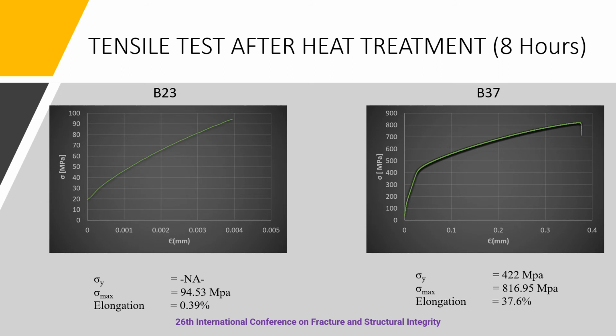When we carried out the tensile test on both the alloys after 8 hours of heat treatment, the nature of B37 did not change, while the nature of B23 changed completely. After the heat treatment, the yield strength of B37 was 422 megapascal, while the ultimate strength and elongation were 817 megapascal and 38% respectively. But when B23 was subjected to heat treatment, the alloy became very brittle and broke with very little load without going into the plastic region.